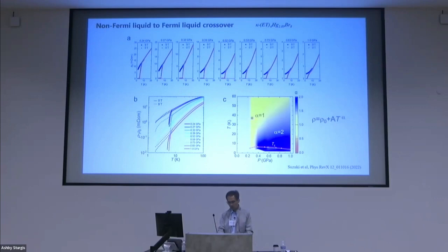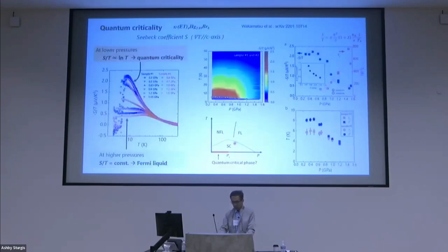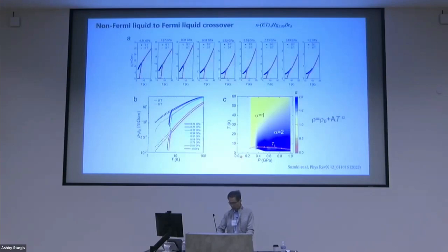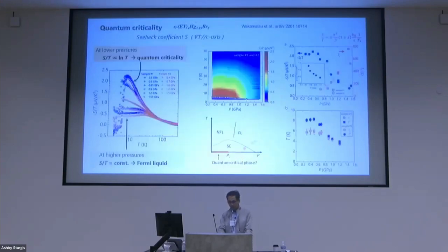We infer that this non-Fermi liquid behavior may be extended at ambient pressure, I think. Okay, in this non-Fermi liquid region, there is quantum criticality. And this color plot shows the intensity of the coefficient divided by T, S over T. And in this region, we see a hotspot. And this is the data of S over T.